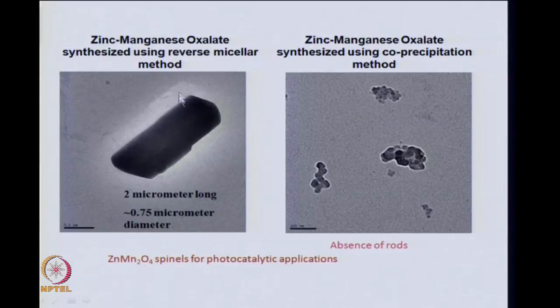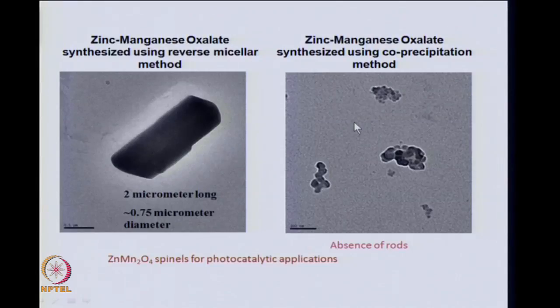So, if you use the reverse micelle method, you get these rod shaped structures. If you do not use the reverse micelle method, no microemulsion, then you get these sphere like structures. Of course, these materials are important and they belong to a structure called the spinel structure and are useful for photocatalytic applications. So, this is one example, but there are many examples we can show where the metal oxalates synthesized using microemulsions show anisotropic or rod like structures compared to spherical or irregular structures if you do not use the microemulsions containing a cationic surfactant.